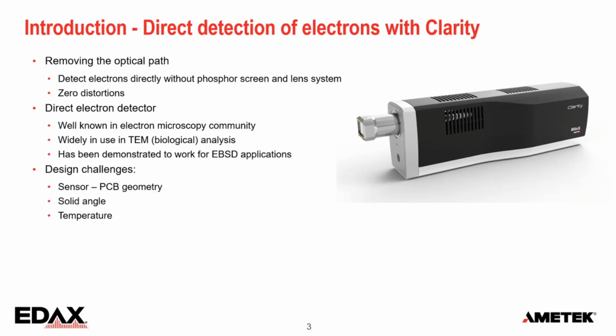One reason was that the sensor, it's just a chip, was sitting on a printed circuit board. And the geometry of that board made it very difficult to position it close to the EBSD sample at the proper tilt angle. So we couldn't get a good solid angle to get enough bands. And maybe even a more important problem was the temperature. It's a CMOS sensor and these sensors get warm. And when you put them on a printed circuit board in the vacuum, then you can work for about 15, 20 minutes and then everything will just get too warm and it cuts out.